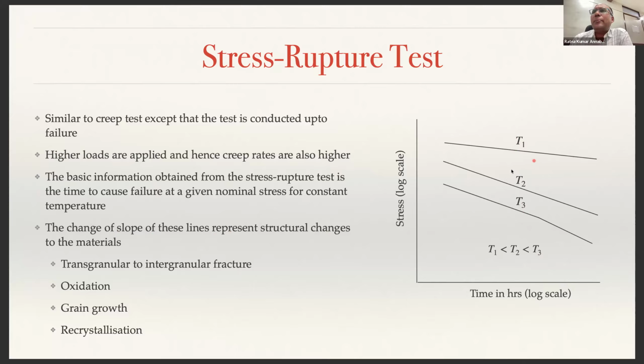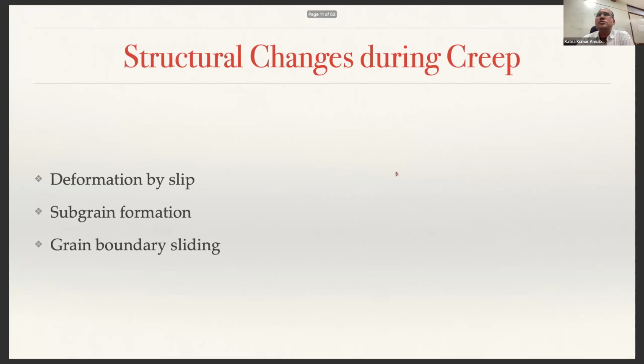So the change in slope of these lines represents different mechanisms or structural changes of the material, such as transgranular or intergranular fracture, oxidation, grain growth, and recrystallization. These are all different mechanisms at play, which cause the change in slope of these lines, or within a given temperature also there can be a mechanism change. You can see here there are two slopes. The structural changes during creep can happen because of deformation by slip, subgrain formation and grain boundary sliding. So you can have slip like what we have discussed in plastic deformation, and you can also have grains within grains, subgrain formation, and grain boundary sliding, because the grain boundaries become weak and might themselves slide. That is also one form of plastic deformation.